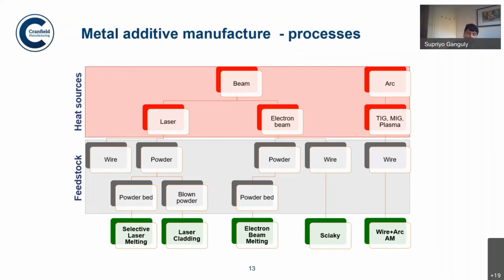Whereas we found that plasma is probably one of the most attractive power source because of the high arc length that plasma can generate, or plasma offers, and which gives the flexibility to add material in it much better than a TIG process. Now, TIG and plasma are essentially same process, where we can control the heat input irrespective of the wire feeding, or it doesn't depend on how much wire we feed. So the wire feeding rate and the power input or the heat input from a process are decoupled. Whereas in GMAW or MIG process, this is basically coupled.